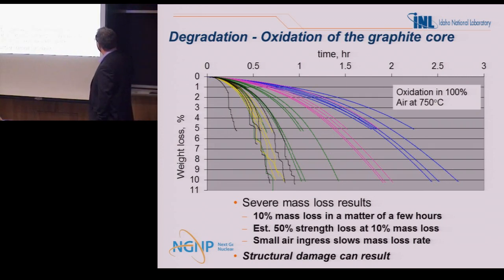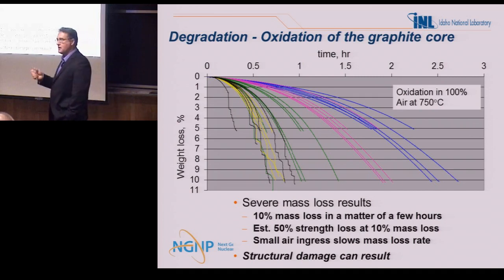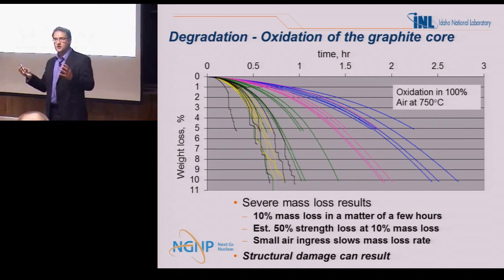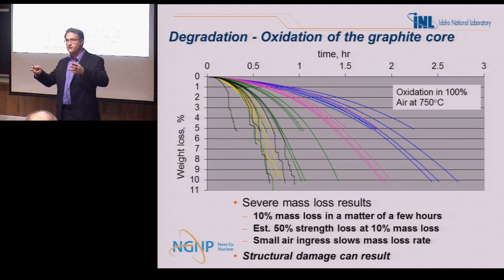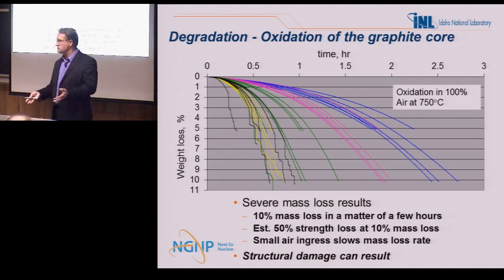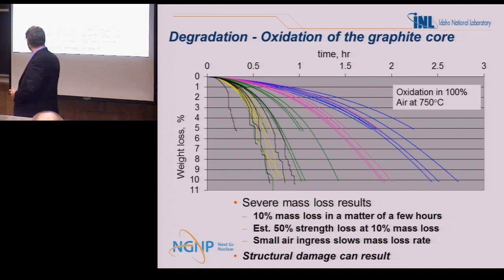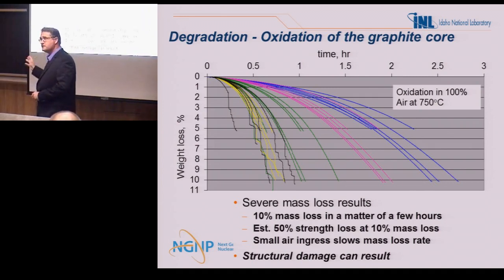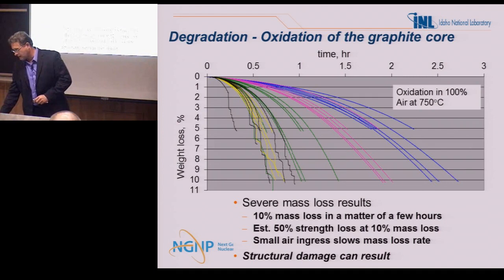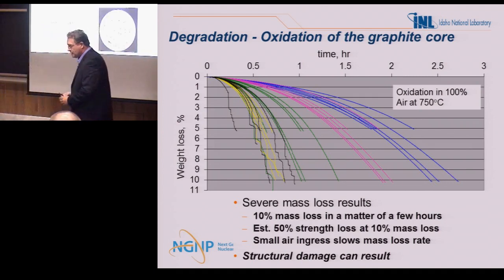Within a matter of an hour or 3 hours or so, you've got 10% mass loss, which can equal, roughly, about rule of thumb, 50% strength loss in your graphite. That's a big deal when you're talking about 100 metric tons of graphite, which is sitting there being held up by graphite columns. It could settle down. We need to understand what the rate is and figure out how to mitigate that.